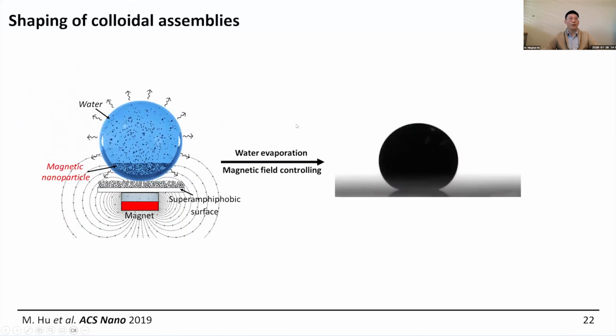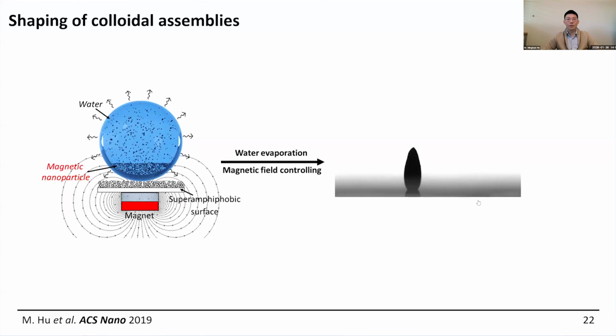To realize that, we use the magnetic field to control the shape. To do that, we have the magnetic nanoparticles inside the droplets. Then we put it on the super amphiphobic surface, which will not spread the droplets, but instead will maintain the spherical shapes. And we can see from this video, during the water evaporation, in the beginning the droplet will maintain this spherical shape. But with time, because the magnetic nanoparticle concentration increases, the magnetic force also increases, so it can break the symmetry to end up with these anisotropic shapes.